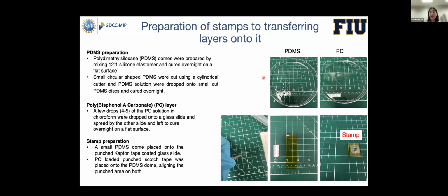And then using the same PDMS solution, we dropped two to three drops onto these cut circular-shaped PDMS domes, and then we kept it overnight to cure, and that's how we prepared the PDMS domes. And the second one is the PC layer, which is the polybisphenol A carbonate layer.